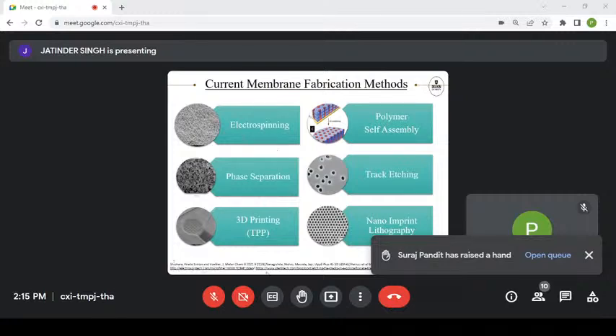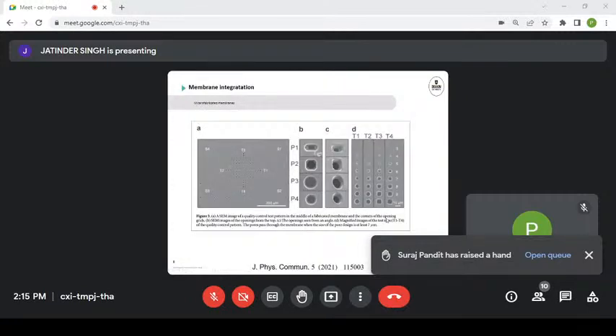We can even go to two-photon lithography, two-photon 3D printing, or nano-imprint lithography, all ways to make small structures. And we'll be looking at a couple of different ways of making membranes, starting off with microfabricated membranes. So here we can see a couple of holes that were made in a PDMS membrane. There was a template made by using positive structures, and these holes in this case were a test piece, so the locations are not that important, but for the application they had in mind, they tried to microfabricate the pores in the areas they wanted to have pores in their assembled microfluidic device.